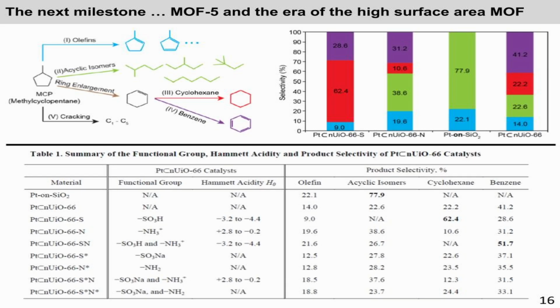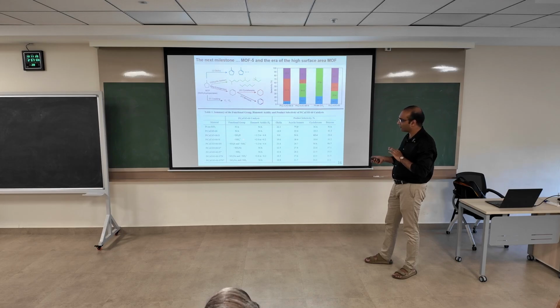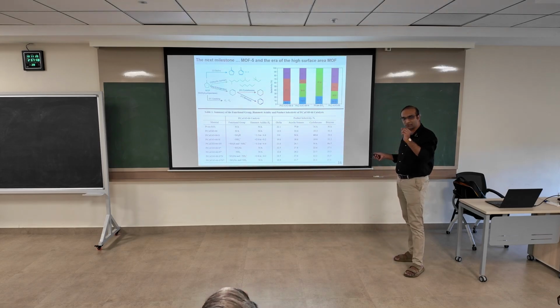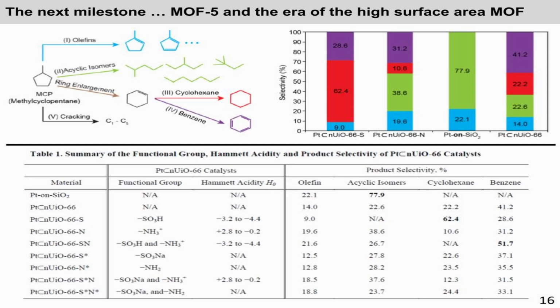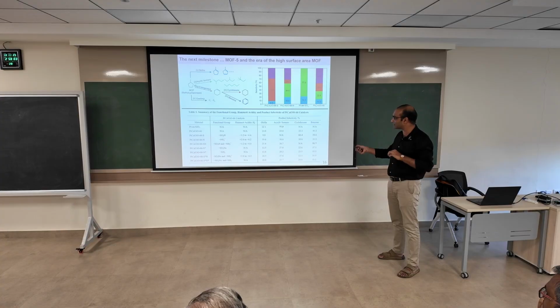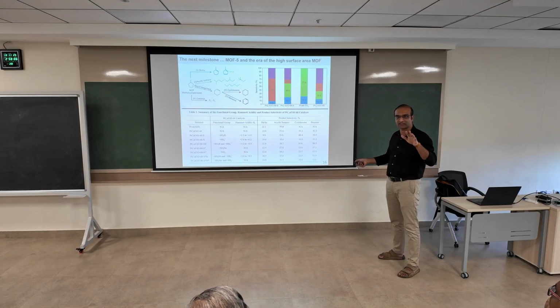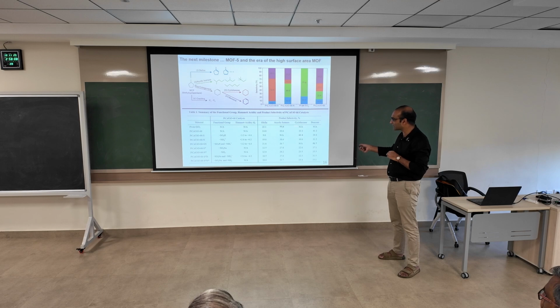For example, if this is a control catalyst, okay, if you just put platinum on silica, you'll mostly get hydrocarbons, like only these acyclic isomers. Okay, you won't get cyclohexane, you won't get benzene. Whereas if you play around with the acidity, if you change the functional groups, you can change the distribution of the products. You can get more cyclohexane and more benzene and more aromatic compounds and reduce the amount of acyclic isomers. Like for example, in this particular case, where you had a sulfide linkage and you had SO3H, you can exclusively make sure no amount of this acyclic isomer, like linear chain hydrocarbons or branched hydrocarbons, forms. Okay. See, with platinum, there's no control. Okay, it almost always gives you acyclic isomers, right?